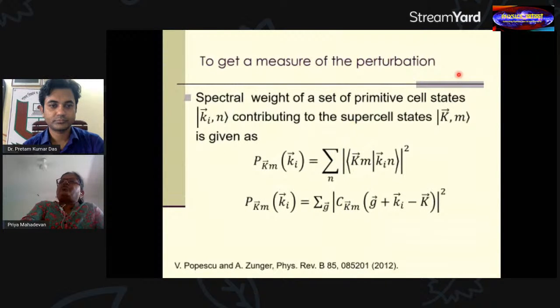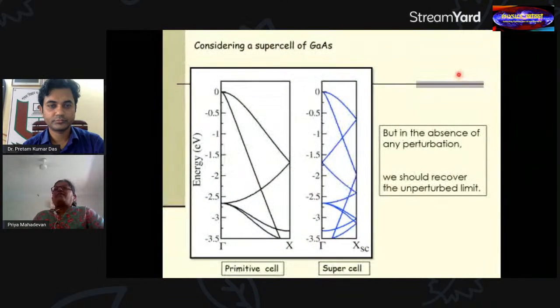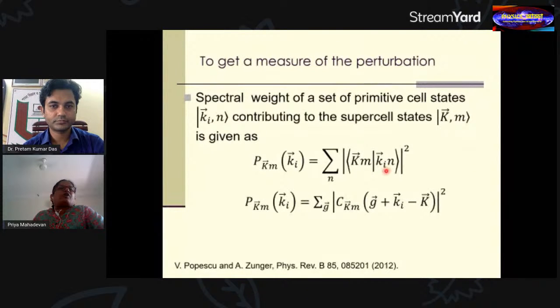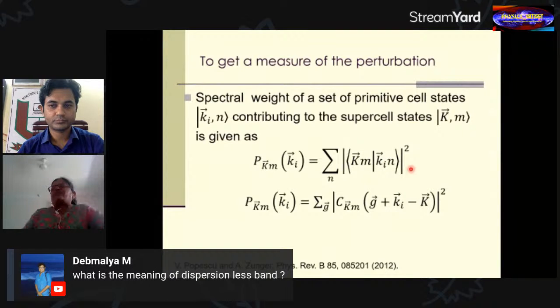So there are ways I can go about this. I can find out what the perturbation is in this case and add that to the unperturbed Hamiltonian, and go to several orders of perturbation theory to get my final eigenstates. The other way of doing it is a method where I project the final state onto my initial state. The ones which are eigenstates get projected and give unity, and those which are not eigenstates of the primitive cell, the unperturbed limit, do not contribute.